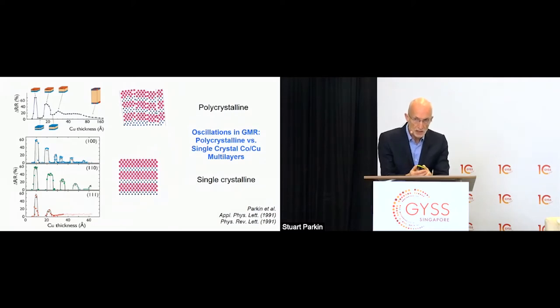And it also showed, as in this case here, depending upon the crystal orientation of the superlattice, whether 100 or 110 or 111, the period of this oscillation varies. And without going into too many details, the period of the oscillation in the magnitude of the GMR is reflective of the electronic structure of this material. In fact, these periods correspond to wave vectors that span the Fermi surface of copper in those particular directions. And these oscillations are actually reflective of an oscillation in the magnetic coupling between the successive magnetic layers that depends on the thickness of the copper layer.